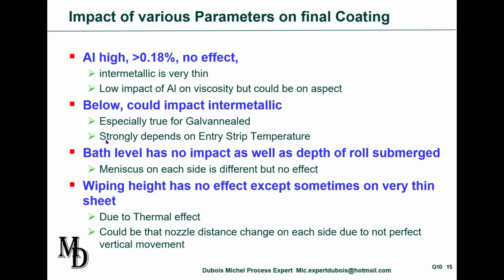As soon as it's higher than 0.18, because the intermetallic is very thin, of course, and because, as I showed you on a previous slide, aluminium has a limited effect on viscosity, it's not going to have any effect. Of course, if you are running 3% aluminium, in the zinc magnesium case the issue is different.